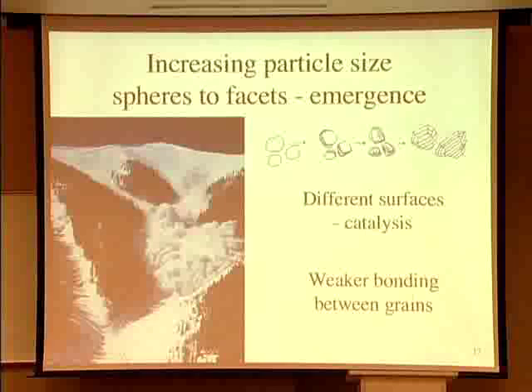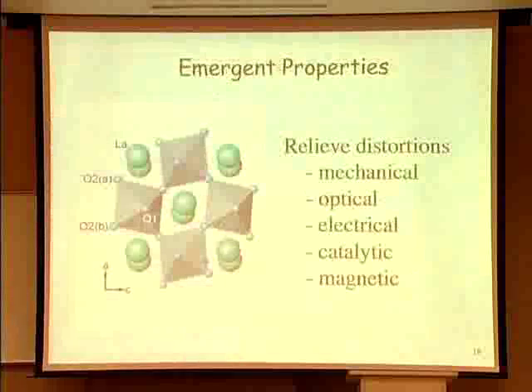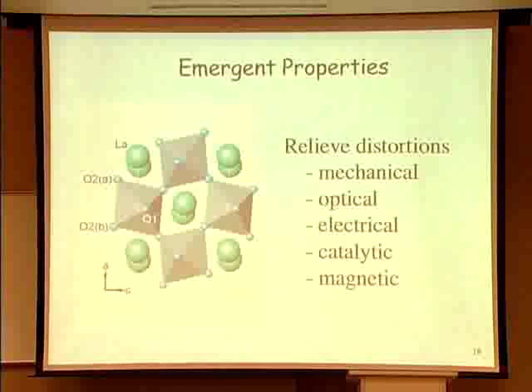Let me give you another example, and this is what we look for in the sciences. We look for materials that in the bulk have some kind of frustration built into them, and that frustration is relieved when I get small. So here's an example of something exciting in my field. It's just lanthanum atoms and oxygen atoms, with a little bit of manganese inside of it. It's become what drives the new computer memories: lanthanum, calcium, manganese oxide, the manganates. But you can see when I make a lot of it, I don't quite have enough room for all the atoms, and so they kind of buckle around a little bit in order to make it fit.